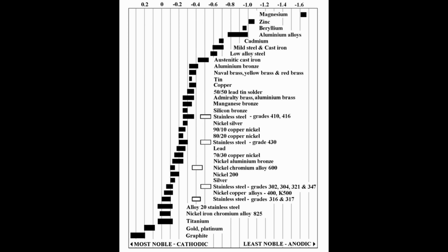The amount of corrosion depends on which metals you're using. So different metals have different kind of galvanic corrosion potential. The further apart they are on this chart, the more they will corrode each other. Now, unfortunately, if we look at the chart, we can see that stainless steel, in our case we're using an 18-8 shoulder bolt, which is basically a 304 stainless, is pretty distant from aluminum on the chart. So there is a decent chance that if an electrolyte becomes present, we might see galvanic corrosion between this shoulder bolt and our aluminum hinge.